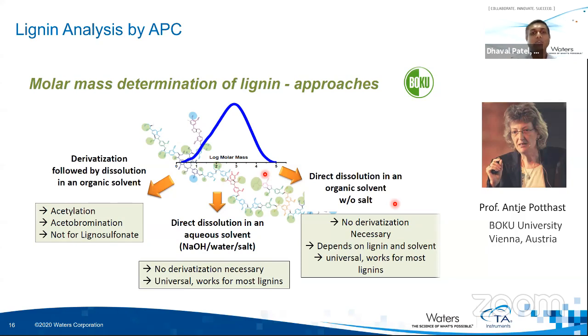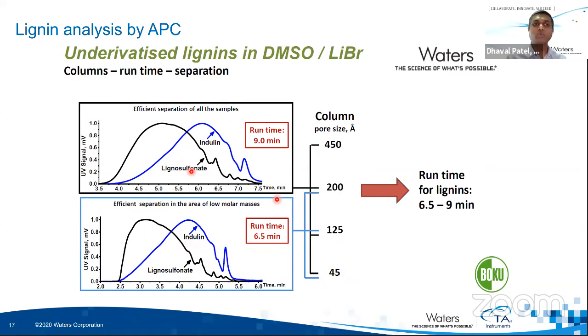Here, you don't really need any derivatization. However, it may or may not work for most solvents. And another approach is using an aqueous solvent. So one of the approaches they use in their lab is they do underivatized lignin by dissolving it in a combination of DMSO and lithium bromide.